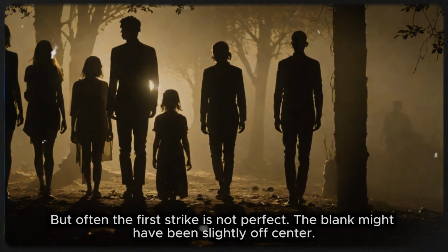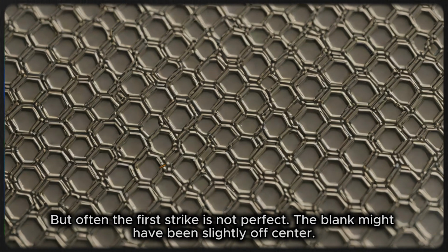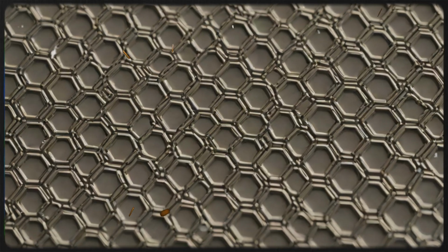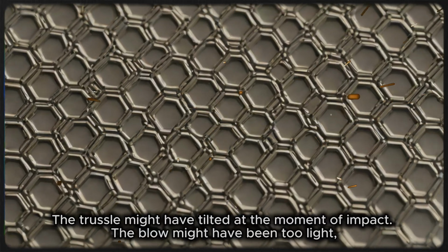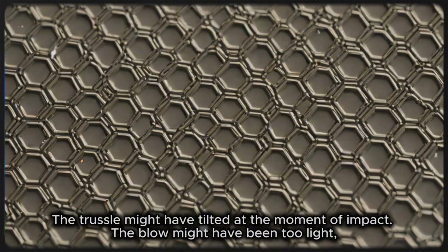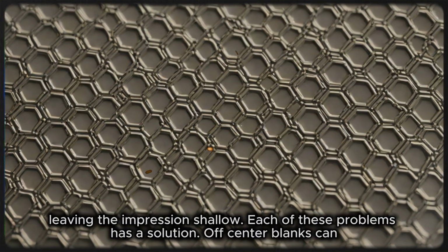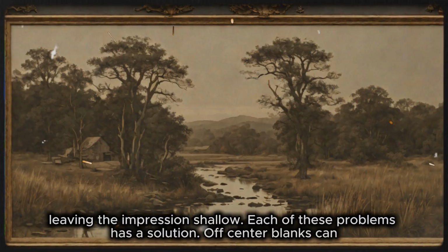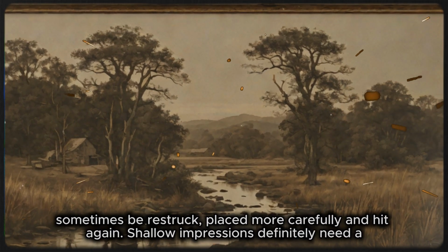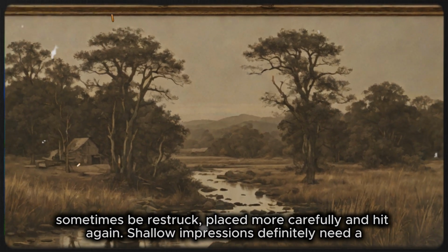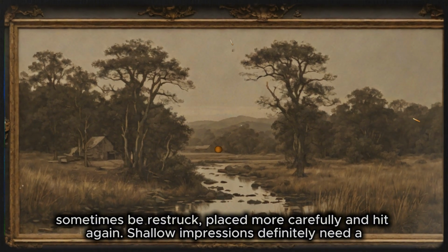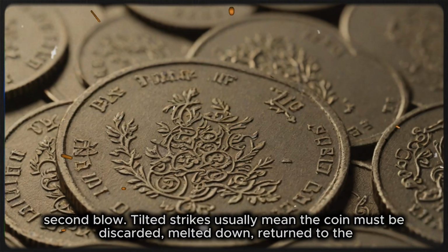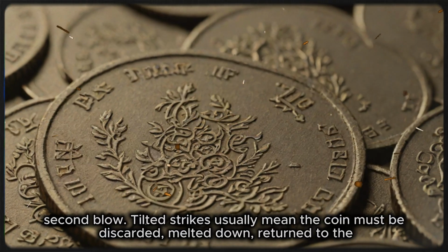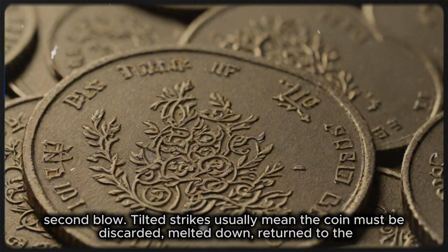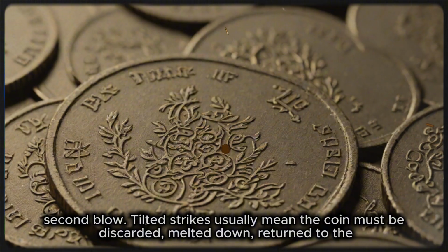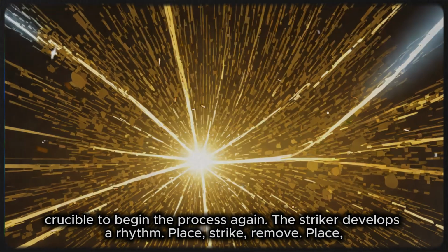But often the first strike is not perfect. The blank might have been slightly off-center. The trussel might have tilted at the moment of impact. The blow might have been too light, leaving the impression shallow. Each of these problems has a solution. Off-center blanks can sometimes be restruck, placed more carefully, and hit again. Shallow impressions definitely need a second blow. Tilted strikes usually mean the coin must be discarded, melted down, returned to the crucible to begin the process again.